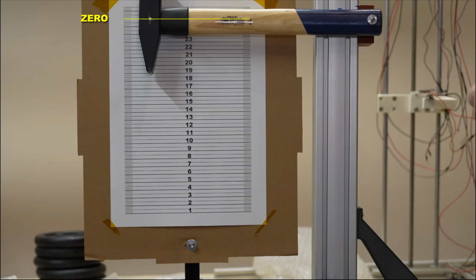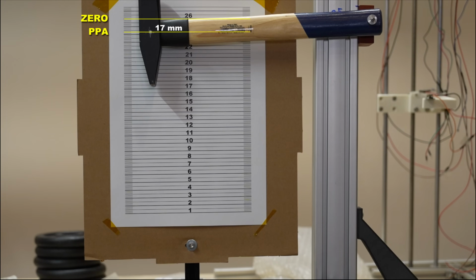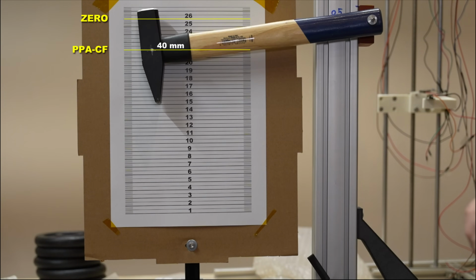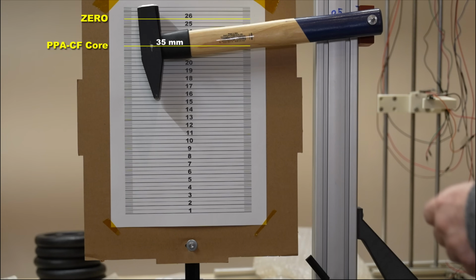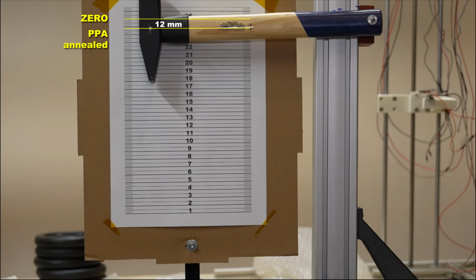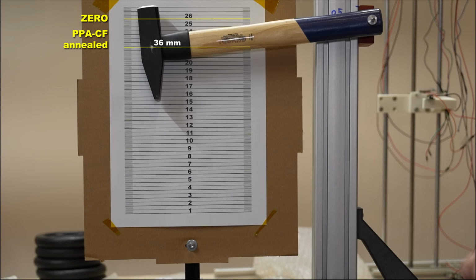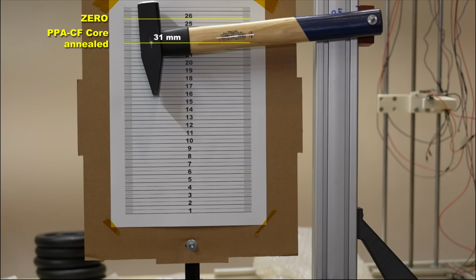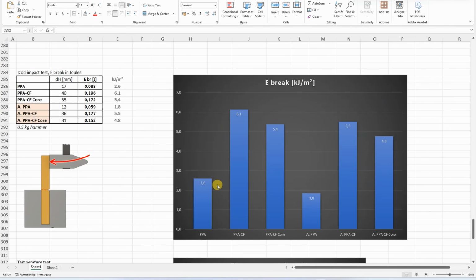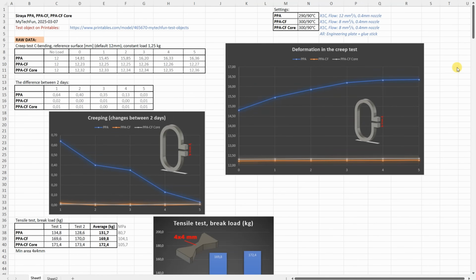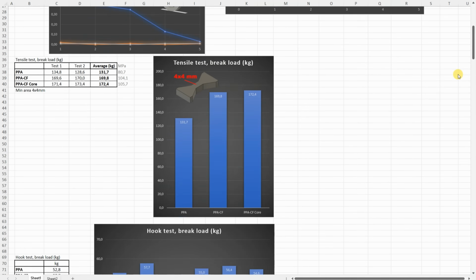Let's analyze the footage. This is the zero position after breaking PPA, PPA-CF, Core version, and this is annealed PPA, annealed PPA-CF, and annealed Core version. We heard that the base material is more brittle compared to the carbon fiber versions, and again the effect of the annealing is not significant. And our results one more time without any additional comments.